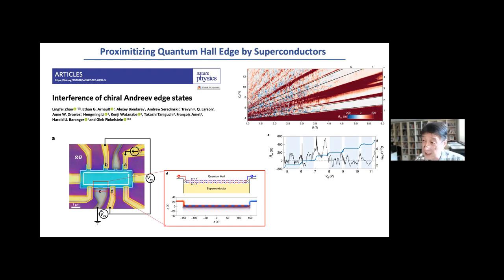Indeed, what the Finkelstein group actually observed is, if you carefully monitor the downstream quantum chemical potentials, you see that there are a lot of well-defined fluctuations of the chemical potential of the downstream of the quantum edges, more like a symmetric C-shape from zero, with positive and negative values rapidly oscillating. Part of the reason is that as you change the gate voltage or magnetic field, whether an electron comes out or a hole comes out depends on the details of the system, right? So while you see that there is the Andreev edge process or Andreev states, the edge state that forms along the superconductor, this may not be too useful for now, right?